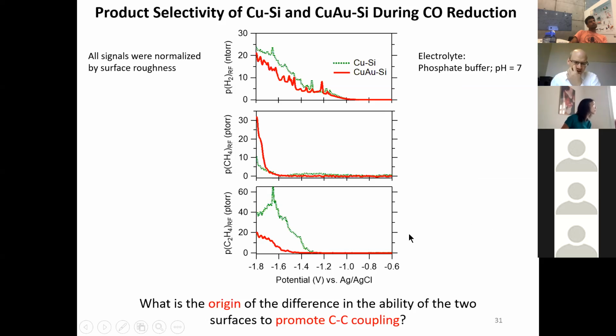Right. So again, we're trying to work on that flow cell, with which we could then certainly answer these questions. Also, you can see that for the copper gold, the onset potential is very similar, but this one produces apparently more methane. And if you look at the supporting information of our paper, we repeated, I think, each measurement 3 or 4 times. I can't remember exactly, but this result also seems quite consistent. We didn't interpret it, but it would also be consistent that 111 produces more methane than ethylene. So there are some features in there where you can potentially at least qualitatively say, yes, there's a higher turnover, but how much that is, I would be careful. Okay, thank you.